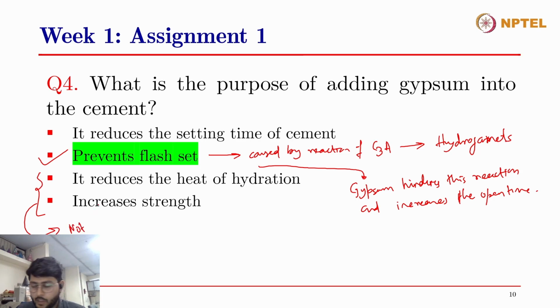Now I won't rule out the last two options, that it reduces the heat of hydration or it increases the strength. These are not completely wrong, because when we add gypsum, the heat of hydration or the heat peaks that we obtain could be slightly lowered depending on the total amount of gypsum we are adding. If we have excess gypsum, then it will retard the system completely and the heat of hydration will also reduce. And when there is no gypsum and hydrogarnets are getting formed, when we add gypsum, since ettringite is formed not instantaneously, rather it forms throughout a duration, that increases the strength.